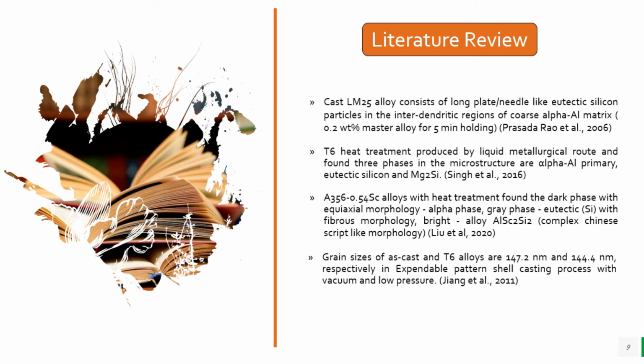Next, from Liu et al., in the study about the A356 with 0.54 scandium alloy and with heat treatment, they found the dark phase with equiaxial morphology is an alpha phase. Gray phase is a eutectic with fibrous morphology. And lastly is a bright phase, which is an alloy of aluminium, scandium, and silicon with a complex